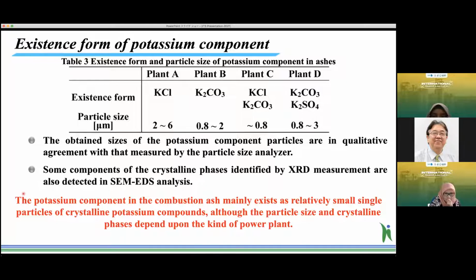Accordingly, these experimental findings lead to the conclusion that the potassium component in the combustion ash mainly exists as relatively small, single particles of crystalline potassium components. Although the particle size is different, for this reason, the potassium-enriched ash can be obtained by collecting the finer ash selectively using a particle size classifier.